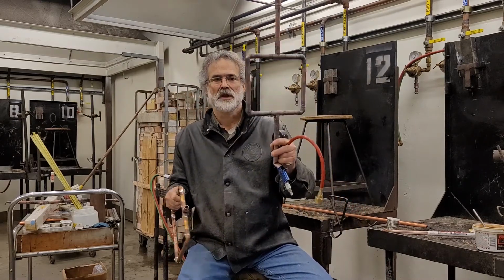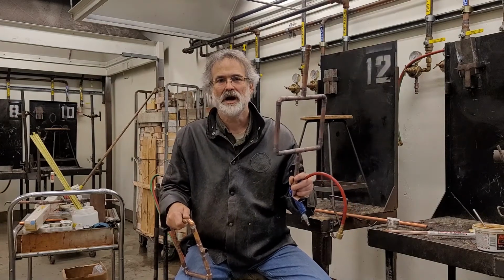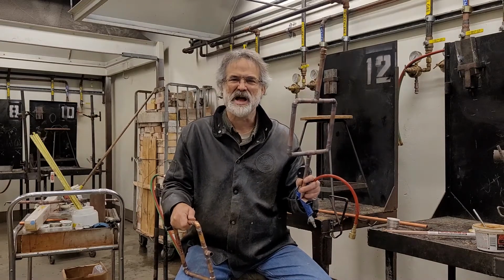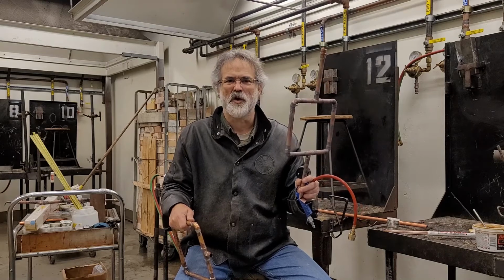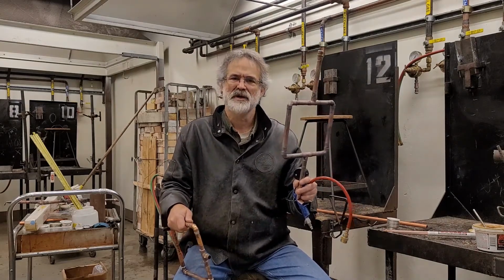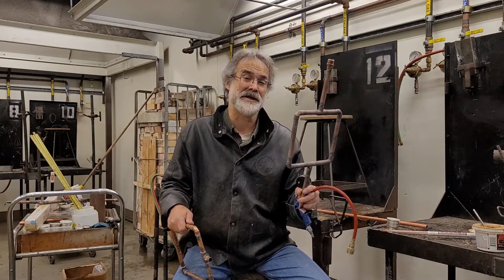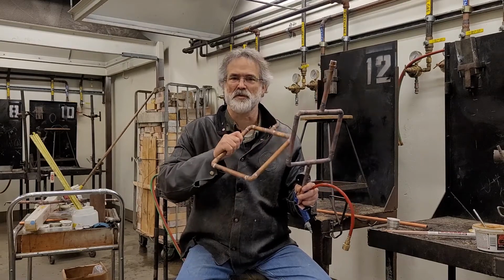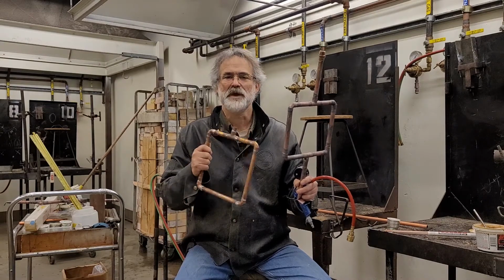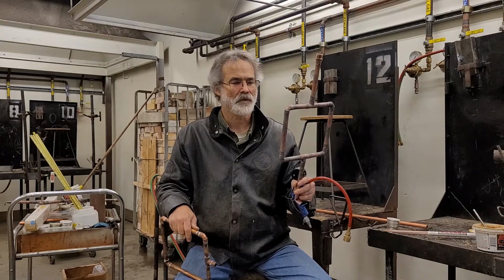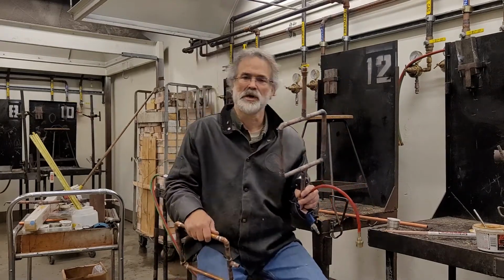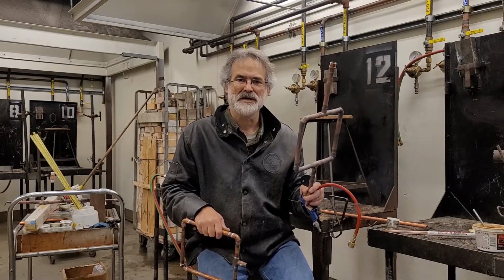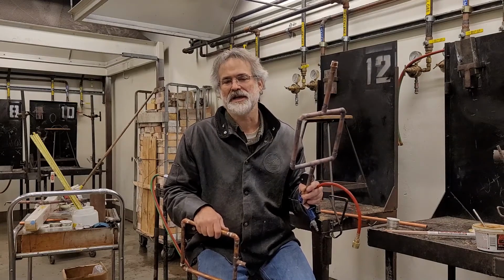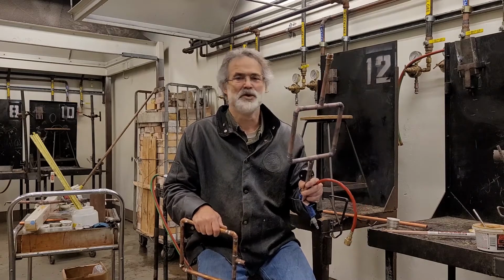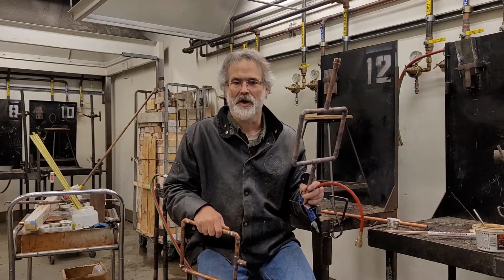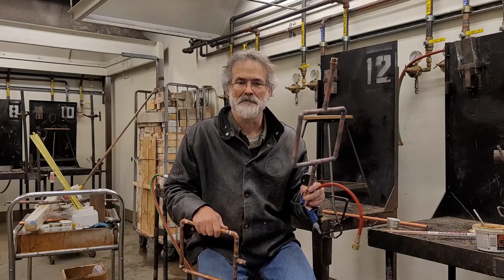The big problem with this one is we got to get the pipe so hot when we're putting it together that the copper actually turns red hot. It starts turning orange. And when the copper pipe starts turning orange, it's not very far away from making a hole in the pipe because this is a thin wall copper pipe. A lot of times people will burn a hole right through the copper. And what we want to remember is that when we're working with an acetylene torch, that flame is really hot, it heats things up really fast, and so we got to keep that torch moving around. All right? If we move the torch around on the pipe, we won't make a hole. The holes happen when people stop moving around.